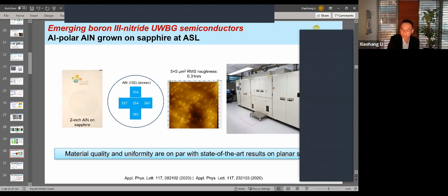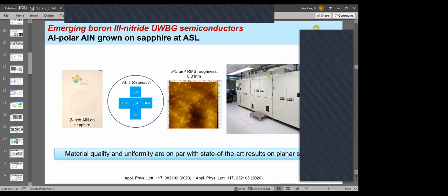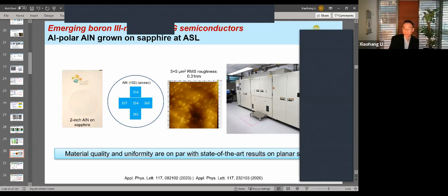So first of all, we have not grown on the binary wurtzite boron nitride, but we have grown the boron aluminum nitride, right? So the boron aluminum nitride is still wurtzite. But if you have wurtzite boron nitride, it's not going to be hexagonal, because wurtzite structure is different from hexagonal structure. Right? So it has a hexagonal basal plane, but it is a little bit more complex compared to the pure hexagonal structure.